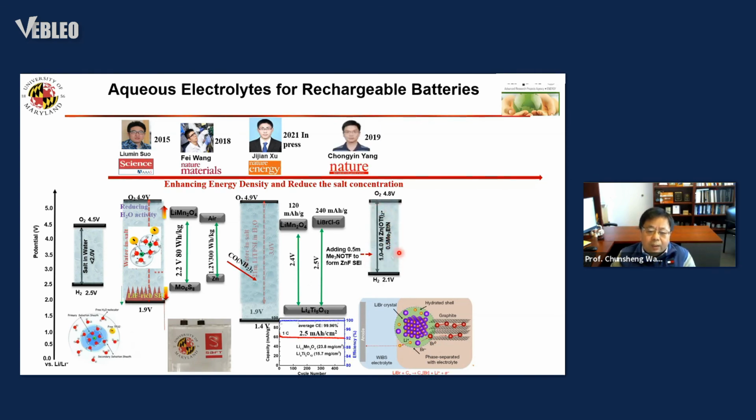And with the same principle as the last slide, we show magnesium and multivalent batteries. The best way is no SEI. If you really want to form an SEI, the only way is ceramic. And so for zinc in the aqueous, they have the same problem. We do not want them to form zinc dendrite, but you have to form an SEI. For zinc, only a fluoride SEI will block zinc dendrite.